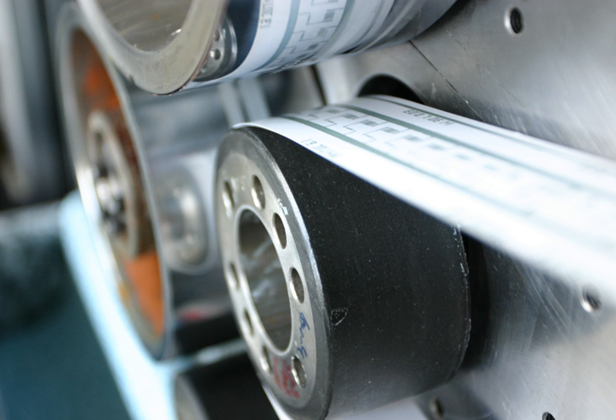Inkjets are flexible and versatile, and can be set up with relatively low effort. However, inkjets offer lower throughput of around 100 square meters per hour and lower resolution, ca. 50 micrometers. It is well suited for low viscosity, soluble materials like organic semiconductors. With high viscosity materials, like organic dielectrics, and dispersed particles, like inorganic metal inks, difficulties due to nozzle clogging occur.